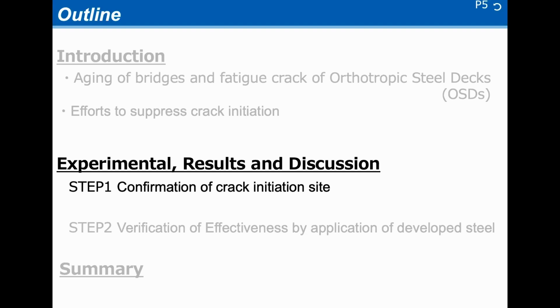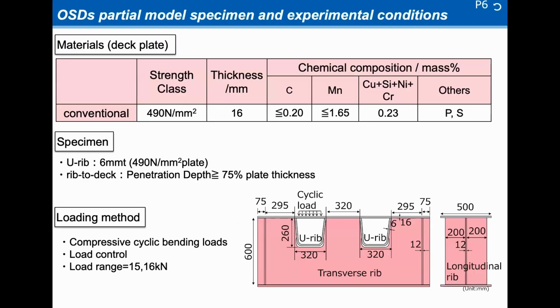Experimental result and discussion. First, confirmation of the crack initiation site. A schematic representation of the test specimen is shown at the bottom. It's composed of deck plate, U-rib, transverse rib, and longitudinal rib, simulating OSDs. The material of the deck plate is conventional steel. Strength class is 490 N/mm² and 16 millimeters thick. And the U-rib is 6 millimeters thick, and the joints of rib-to-deck were welded so that penetration depth becomes 75% or more of plate thickness.